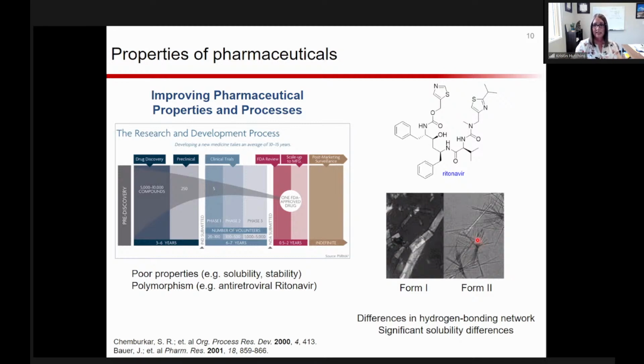What was problematic is that form 2 exhibited significantly lower aqueous solubility than form 1, which made it problematic when giving it to patients. So in the height of the AIDS crisis, ritonavir had to be pulled from shelves because of this issue, causing a lot of harm to not only patients, but the pharma industry in general. And so polymorph screening, finding polymorphs, and being able to control them is really advantageous.